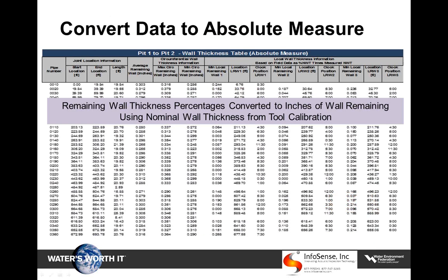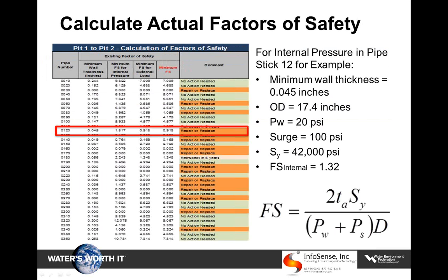The first step in doing this is we converted all the percent wall thicknesses into actual inches using the nominal wall thickness that we got from the calibration test. This allowed us to convert all those percent wall remaining into inches of wall remaining. And then it was fairly easy to back calculate the actual factors of safety that each stick of pipe was affording, because we knew the operating pressures, we knew that we gave an allowance of surge, we knew the wall, the pipe depth, we knew the surface conditions, live and dead loads. We're able to actually calculate the minimum factors of safety against both internal pressure and against external load.